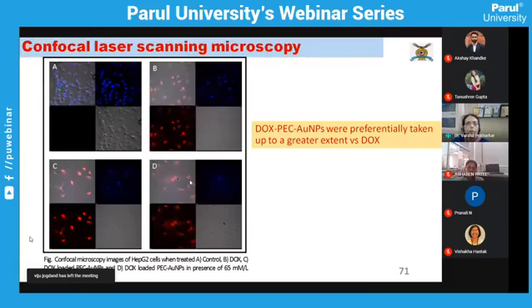The confocal laser scanning microscopy again confirmed the preferential uptake of these DOX loaded pectin reduced gold nanoparticles. You can see here A is for the control, B is for plain DOX, C is for the DOX loaded pectin reduced gold nanoparticles, and D is for the DOX loaded pectin reduced gold nanoparticles in presence of galactose. So you can see that in presence of galactose the intensity has considerably reduced, whereas in absence of galactose the intensity of uptake is very high. So it establishes that they were preferentially taken up to a greater extent as compared to plain DOX.